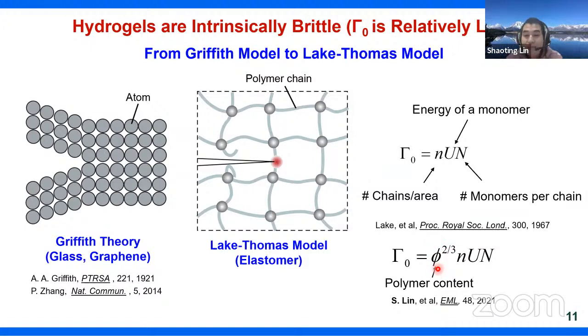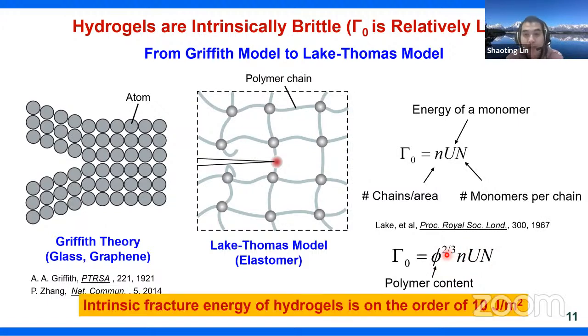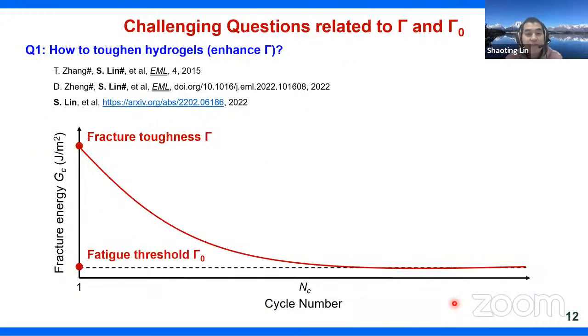So by putting in real physical parameters for hydrogels, we can estimate that the intrinsic fracture energy of hydrogel is typically on the order of 10 joules per meter square. This is actually a pretty low number. You can just imagine, for metals, the fracture toughness is typically on the order of 10 to the power of 4 or 5 joules per meter square. So then the first question we want to answer is, can we enhance the fracture toughness of hydrogels from a relatively low number gamma naught to a relatively high number gamma that is comparable with elastomers?